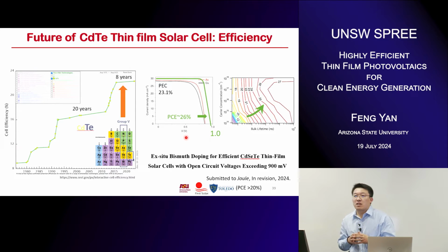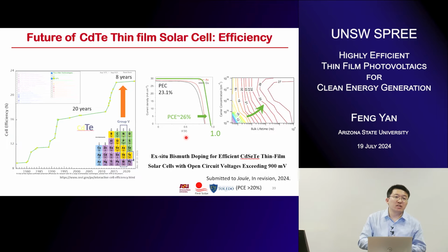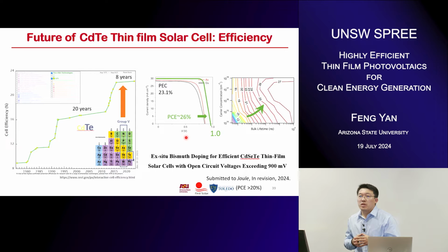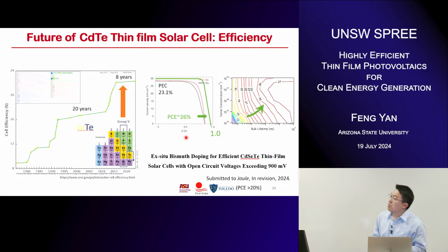After this arsenic chloride, we continued the collaboration and initiated a research agreement with First Solar, and we demonstrated that using bismuth can reach around 900 millivolts, and this work is in revision right now. Hopefully we can further continue this, and we have an ongoing research project working with NREL to continue this group 5 doping in cadmium telluride, and we have some other techniques to further realize this technique.